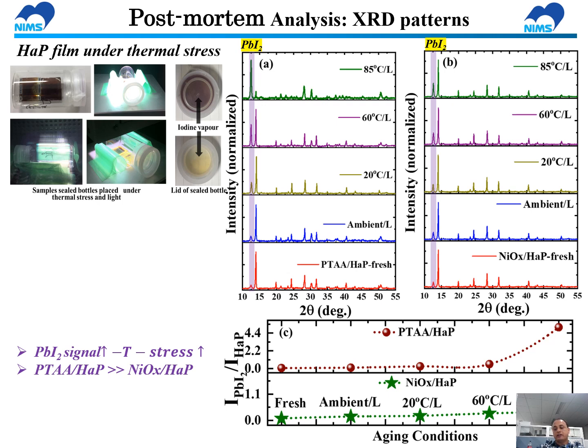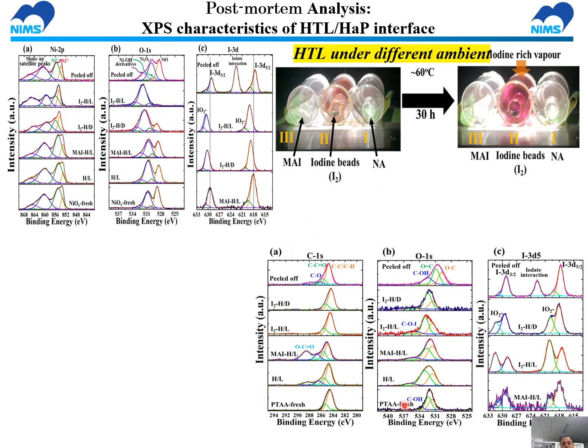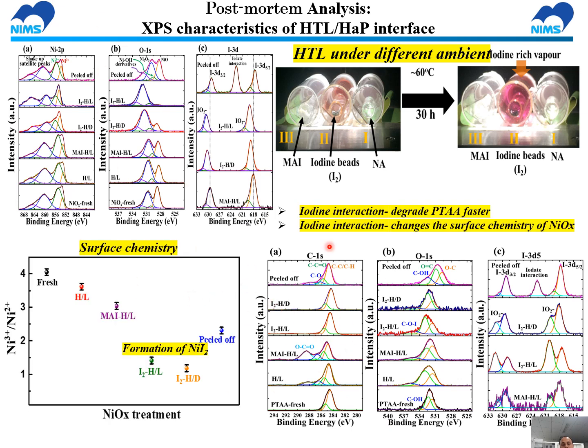Moreover, we also collected the XPS spectra of different ETL and HTL layers, that is PTAA, nickel oxide, and PCBM, placed under different ambient conditions, iodine rich or MA vapor rich condition. Of course, this slide is very busy. If we see the PTAA layer, it degrades faster with iodine interaction. However, although there is some formation of a very thin layer of nickel iodide and some change in surface oxidation state, nickel oxide still retains its property rather than deteriorating like PTAA, and that's why the device with nickel oxide is comparatively stable.